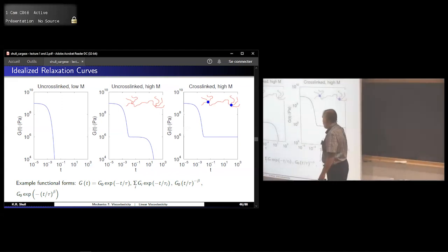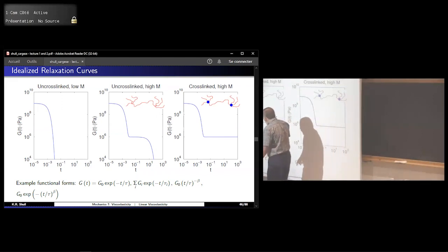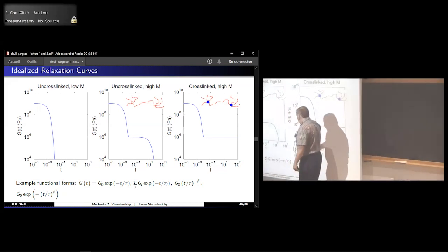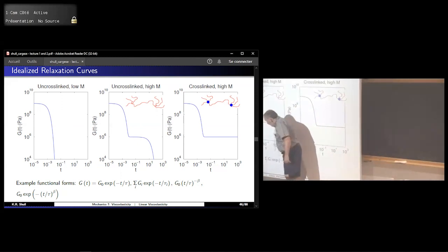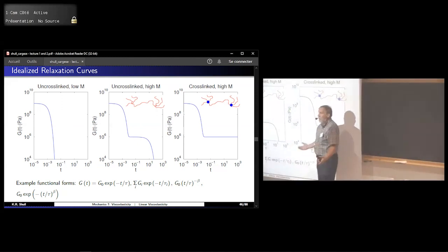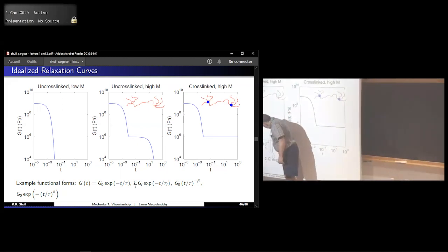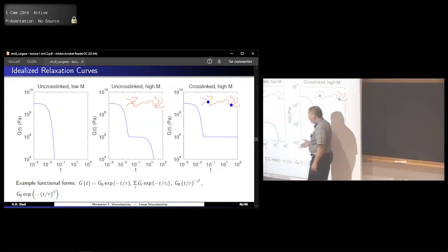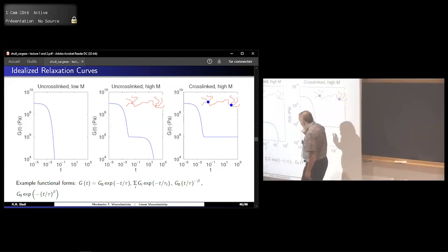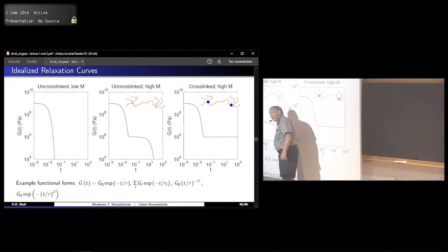And down at the bottom, these are the ways people look at these things. There are cases which are pretty nearly single exponential in their decay, but not that many of them, at least in the solid things I'm more interested in. But if you take enough of these single exponentials and add them up, you can fit anything. And often these relaxation times correspond to specific processes. So this is why a proper rheologist generally likes this the best.